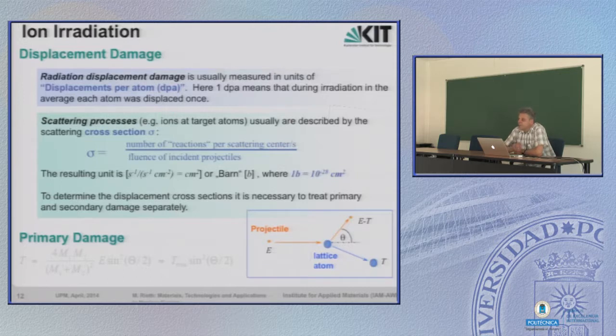A scattering process, that means ions at targeted atoms, usually is described by the cross section. A cross section, that's sigma here, not stress, that's the scattering cross section, gives the number of reactions per scattering center per second, that's the collisions, divided by the fluence of the incident projectiles. So the resulting unit is 1 per second divided by 1 per second and 1 per square centimeter. In the end, it's centimeter square, or barn, that's the physical unit, and 1 barn equals 10 to the minus 28 square centimeters. That's rather theoretical at the moment, but I hope to explain it better in the following sections.